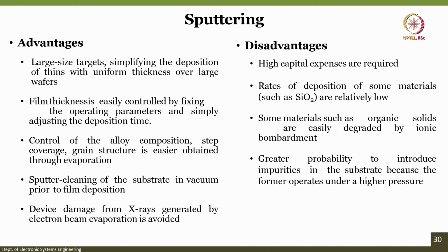So now, if you want to compare sputtering by its advantages and limitations, what are the advantages? First, let us go to the advantages. Larger size targets simplify the deposition of films with uniform thickness over large wafers. That is advantage one. Second, film thickness can be easily controlled by fixing the operating parameters and simply adjusting the deposition time. Advantage number three, control of the alloy composition, step coverage and grain structure is easier.